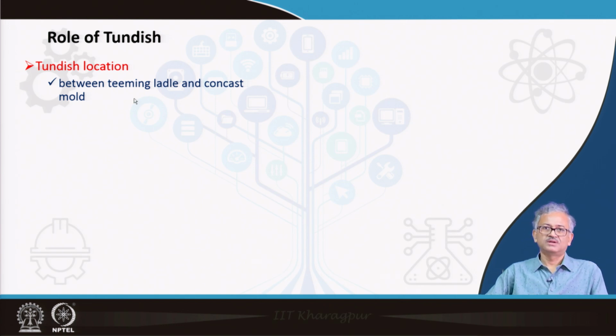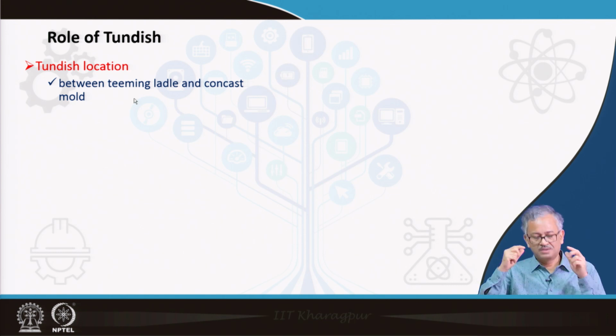Why is the tundish required? Because it is required to provide the liquid steel at a constant flow rate into the mold. Continuous casting is fixed with a constant heat extraction into the mold, so if you change the flow rate, then it will not be able to cast properly. Okay. So, the flow rate should be constant, and that is why if you use the intermediate reactor, you can maintain the height of the liquid in the tundish more or less constant. But if you directly feed the continuous casting mold from the ladle, then obviously the height level will change. As a result, the flow rate at the nozzle exit will differ. Okay, that was the main idea. That is why the tundish is used.